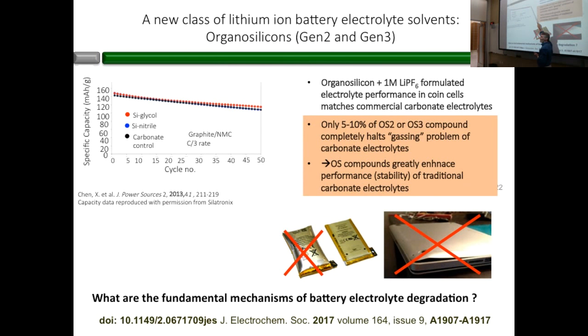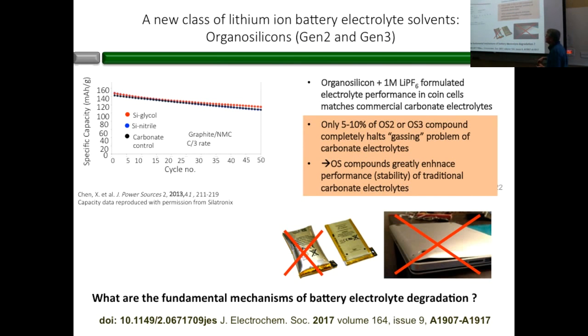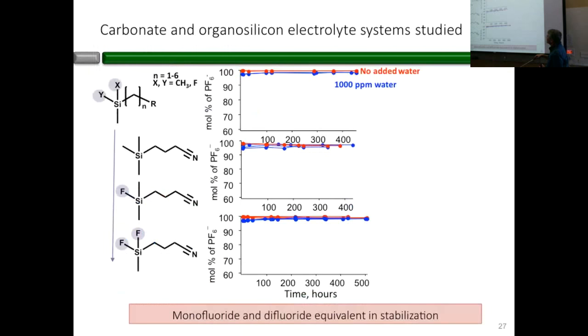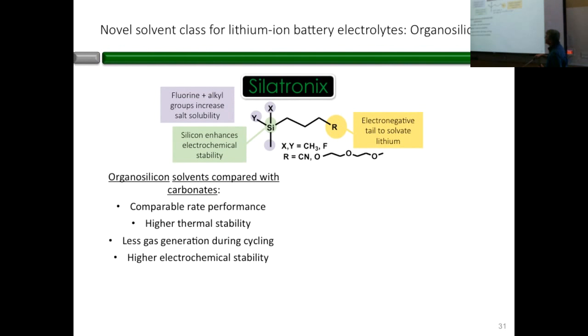Part of the reason for that is that we have less resistance at that electrode interface, and the less resistance is a result of the fact that the lithium chelation with the molecule is a little weaker. Therefore, when the molecule goes out of the solution and back into the electrode, it's a little easier. That results in less resistive losses at the electrode interface and ultimately makes it more stable.